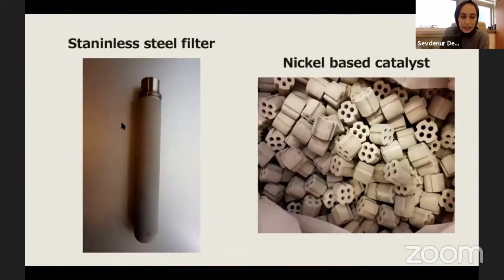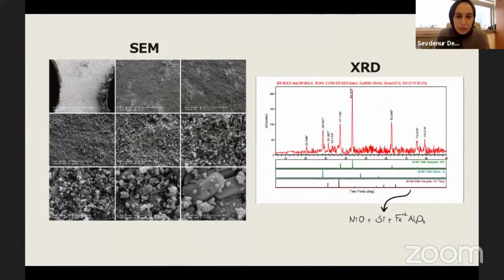Stainless steel filters were used to remove particulate matter, and nickel-based catalyst was preferred for tar removal. The figure on the left shows the result of high-resolution scanning electron microscopy analysis for nickel catalyst, and the figure on the right shows the result of X-ray diffraction analysis for nickel-based catalyst. The XRD result shows that the nickel-based catalyst is composed of bunsenite, silicon, and hercynite.